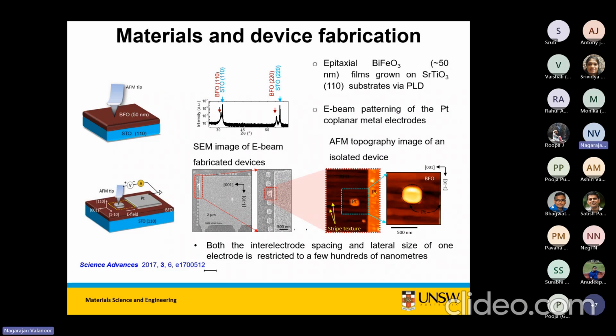So you see here, the BFO is grown on a bottom substrate, but there is no bottom electrode. I know at this time, a lot of big groups were actually having bottom electrode and they were trying to do out-of-plane switching. In-plane switching, actually, if they had done this, they would have won this race rather than us. And you can control that in-plane switching by simply controlling the space between the small electrode and the ground electrode. And you can control the size of that small electrode so that you can control the electric field distribution. You can do all those things.